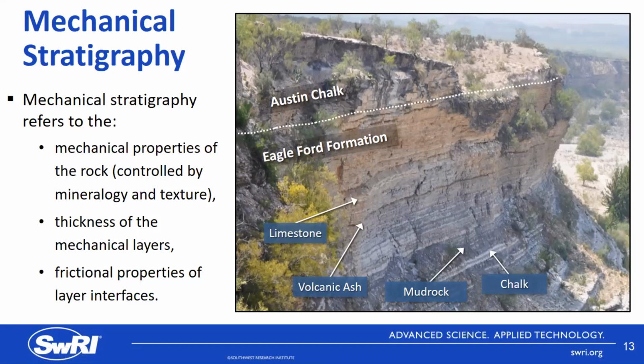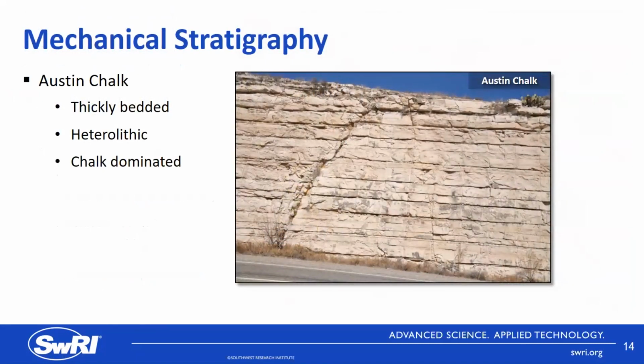It's very sensitive to the mechanical properties of the rock, and in carbonate and mud rock facies, that is very sensitive to the amount of clay. So clay and organic carbon tend to weaken it, and so if it has a little bit of clay, 10 to 15% clay can make an otherwise relatively strong rock relatively weak. The thickness of mechanical layers is also a super important parameter. It often influences fracture height, fault geometry, and so forth. And then the frictional properties of layer interfaces is also important, because a little bit of slip on layer interfaces can stifle vertical fracture propagation.